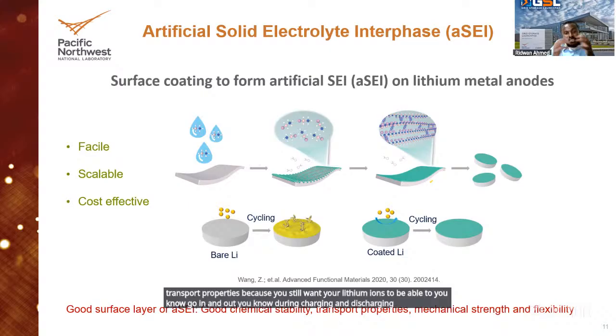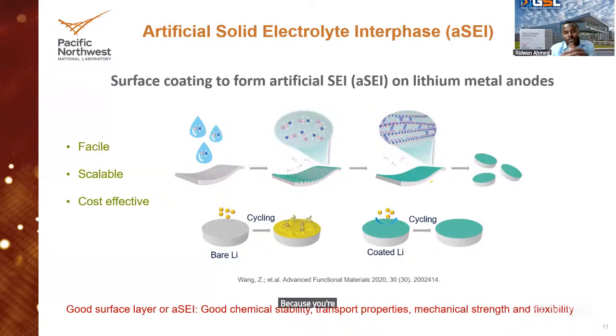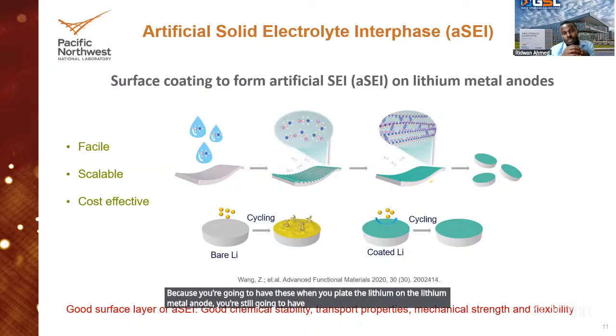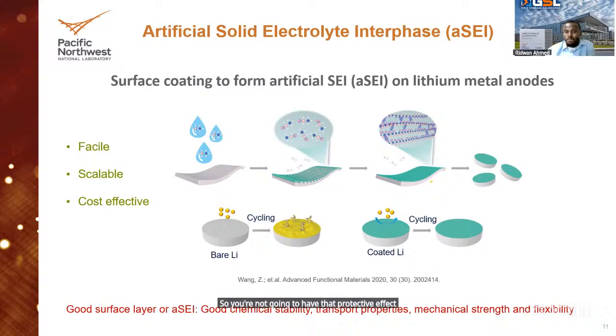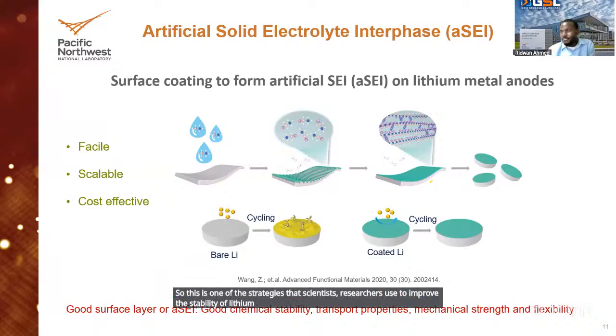And of course, you want it to be robust because when you plate the lithium on the lithium metal anode, you're still going to have this increase in volume, of which if the SEI is not strong enough, it's going to break it. And that's it, it's gone. So you're not going to have that protective effect again. So this is one of the strategies that researchers use to improve the stability of lithium metal batteries.